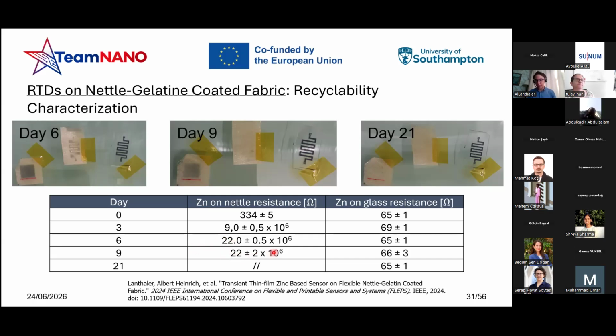And within 21 days, the resistance wasn't measurable anymore. We encountered a loss of content basically. Despite that, the zinc deposited on the glass slide remained constant, meaning that of course there was a formation of the zinc oxide layer, but it wasn't enough to make it completely conductive and to encounter loss of content. The conclusion, of course, is that the gelatin itself started to absorb the zinc on top of it.